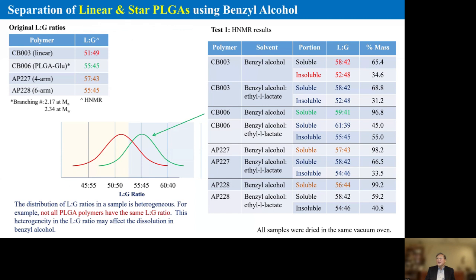Now, this slide is very complicated because of so many numbers, but my main point here is in the figure in the center. If we look at the linear polymer, the LG ratio is 51-49. That's the average of every single PLGA polymer in the sample. But if you look at individual PLGA molecules, their LG ratios may be different. So I just want to point out that the LG ratio, when you look at it from the brochure or catalog, is an average of every single PLGA molecule. So individual molecules may be heterogeneous.